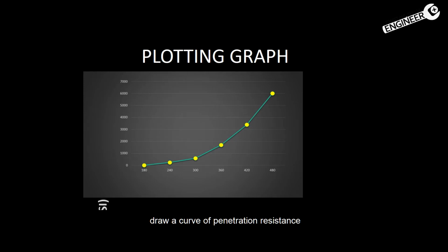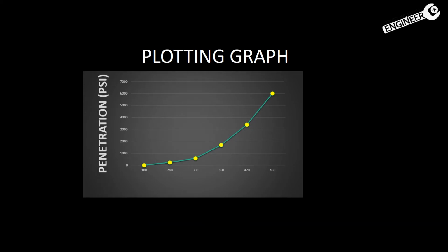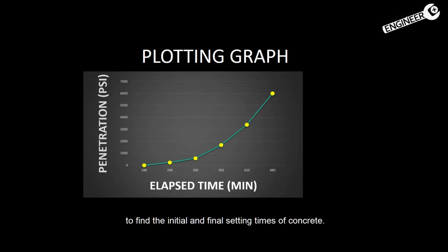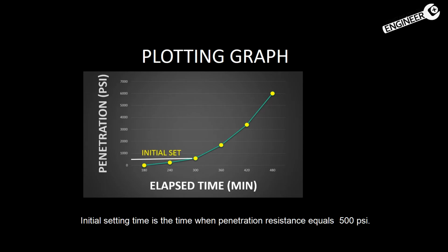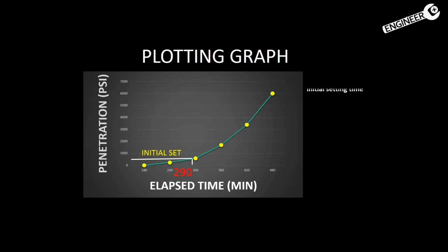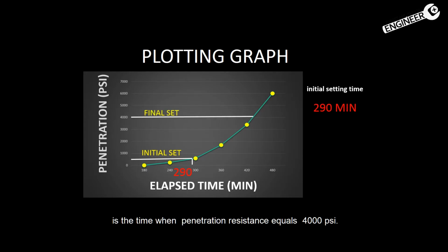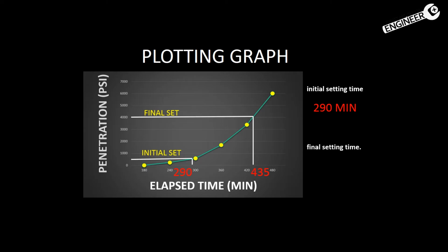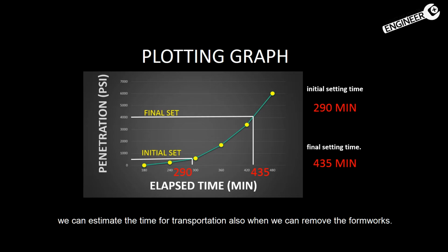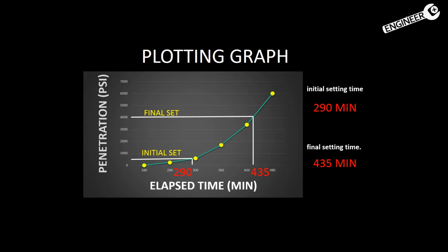After we get 6 penetrations, draw a curve of penetration resistance versus elapsed time to find the initial and final setting times of concrete. Initial setting time is the time when the penetration resistance equals 500 psi, and the final setting time is the time when the penetration resistance equals 4000 psi. So as we know the initial and final setting times, we can estimate the time for transportation and also when we can remove the formworks.